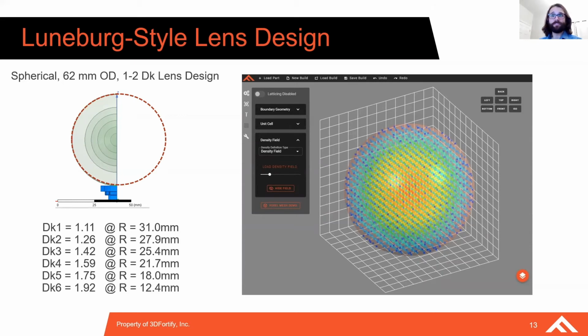The image shows warmer colors towards the center, which represent a higher DK at the core, where the cooler colors on the surface are closer to the permittivity of 1.1 at the surface. So this lens, while it's designed to be Luneburg-like, it's not exactly a 1 to 2 DK lens. It's a 1.1 to 1.92 DK lens.